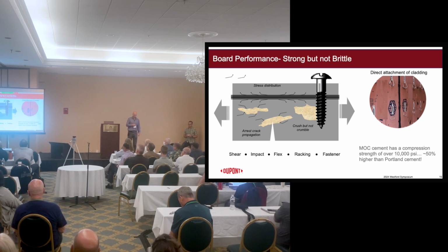Okay, this is where I think the magnesium oxide based boards really start to shine. So these products can be used as a direct structural nail or screw base for most cladding types. And the reason you get that is, most cementitious materials, you try and screw into them, they're quite brittle, and they'll hold a little bit, but they'll break apart as you put a fastener into it. And if you try to increase its toughness, decrease its firmness, it becomes too weak to actually hold fasteners.